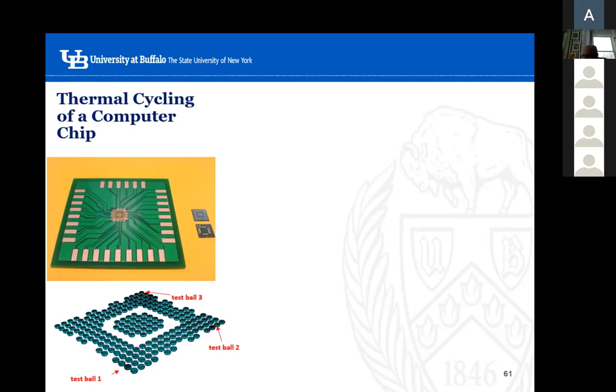Till a stable cycle is there, you just count how many loops afterwards it fails, then multiply the number of loops. This is the total. Every time you are accumulating the energy, you are basically losing the ductility. Every hysteresis loop, the plastic strain is getting accumulated. It is absolute adding. So once it reaches the maximum permissible ductility of the material, it fails.